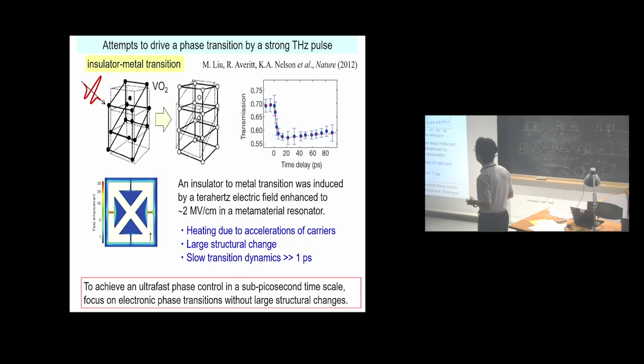Attempts to drive phase transition have also been reported. A typical example is the study on VO2. In this study, an insulator to metal transition was induced by a terahertz electric field enhanced to about 2 megavolts per centimeter in a metamaterial resonator. However, this transition originated from the heating due to the accelerations of carriers by the electric field and was accompanied with large structural changes. In fact, the transition dynamics is much slower than 1 picosecond.